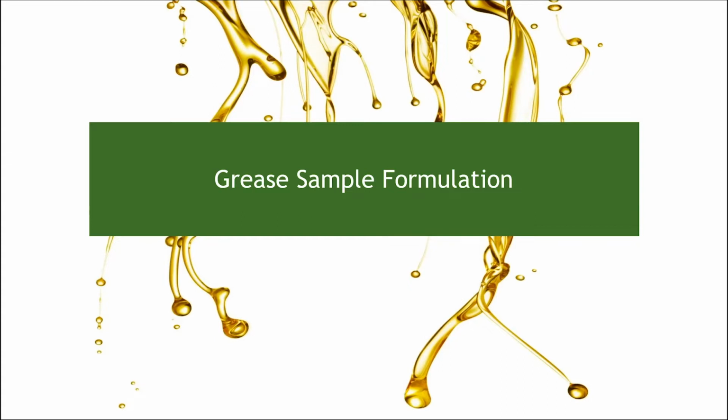As you cook a grease with a bio-based product, especially if it's an ester, you're heating it up to relatively warm temperatures, above 200 C. There's usually some water present from the soap process that goes into it. Water plus heat usually means significant hydrolytic damage, and a lot of times the bio-based products would fall apart before they could be cooked and finished as a grease.